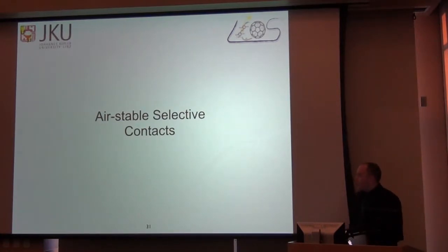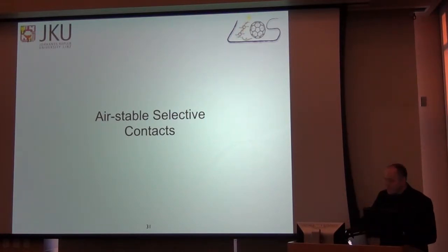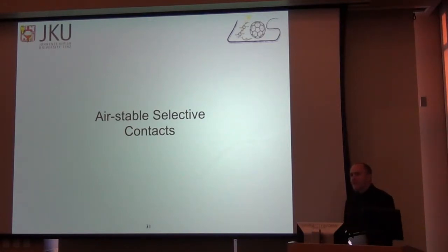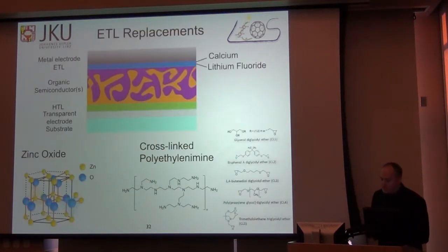So now moving on from background to a little bit of my results over the past maybe 10 years or so that I've been working on these materials. When I started working on them in 2005, one of the biggest knocks on the material was that the efficiencies had just started to come up to respectable values. But if you remove them from a nitrogen-filled glove box, the devices would die within minutes. And so this 30-year module lifetime seemed like a complete fiction. Even though the efficiencies were just starting to become real, this was one of the biggest issues.